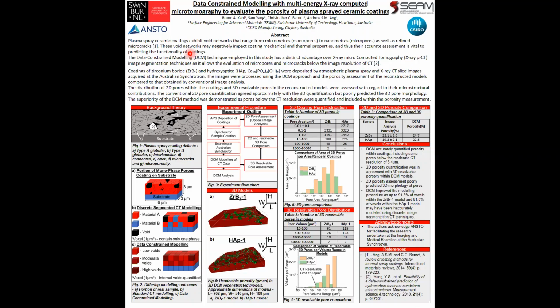The void networks tend to have a negative impact on coating mechanical and thermal properties, and hence the accurate evaluation of voids is vital in predicting the functionality of coatings. The data-constrained modelling technique employed in this study has a significant advantage over traditional micro-CT image segmentation techniques, as it can incorporate fine structure details below the CT resolution and hence evaluate micropores and microcracks.